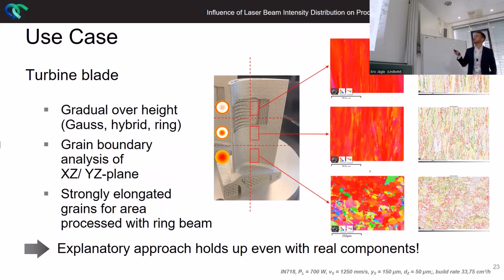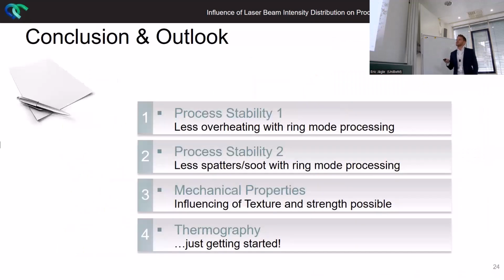That got supported by the grain boundary analysis. So we can see here kind of equiaxed grains in the Z direction for index 0 sample, whereas they are much more elongated for index 6 samples. So by varying the different intensity distributions on the fly, we could influence the growth of the crystals within the process.